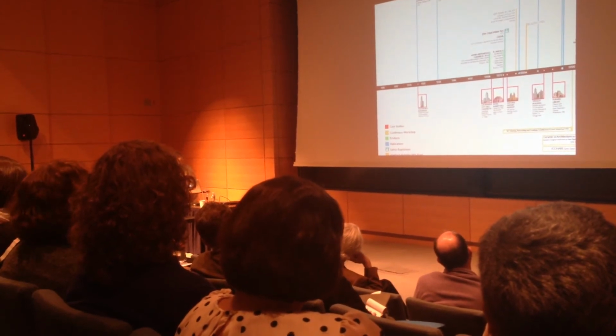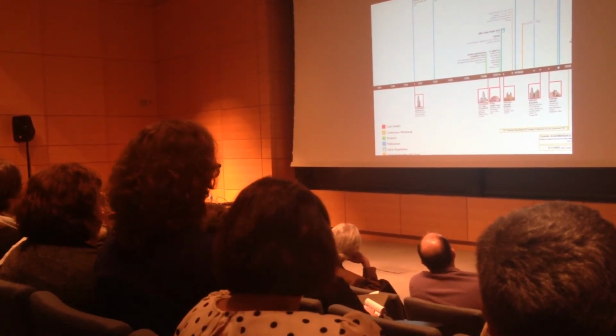Two important case studies need to be mentioned. They are two English case studies where two major buildings were cleaned between the 70s and the 80s: the Royal Albert Hall and the Natural History Museum. Both of these examples represent large scales of perceived damage caused by misuse of wrongly chosen cleaning techniques. The Royal Albert Hall was cleaned with a wet abrasive system, and the Natural History Museum was cleaned with HF-based cleaner.